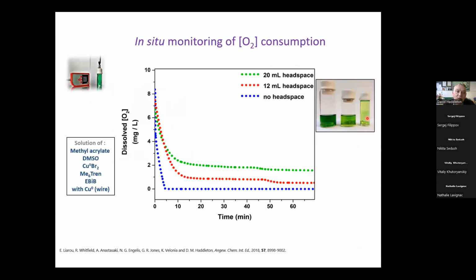And all we've done here is we've got exactly the same reaction, but we've just used smaller and smaller vials, which meant there was less air in there when we put the super seal on. So the more air you've got, the more copper 2 you get. As you reduce the amount of air, you get less copper 2. And when you fill it up, you just see no headspace. The oxygen level is depleted. So the easiest way to deoxygenate, you just fill up your reactor. In our case, we use vials.